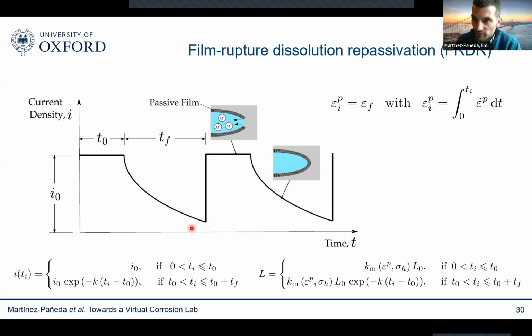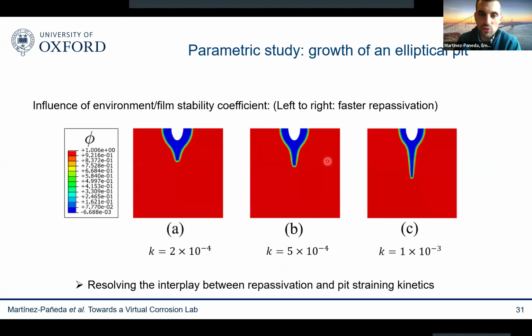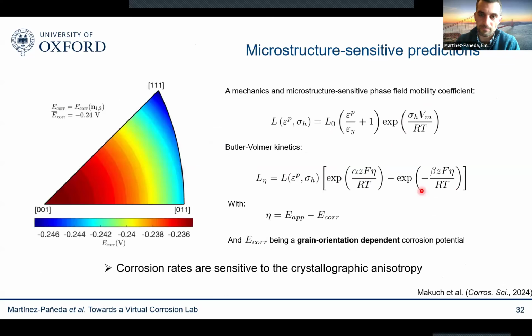And again, we can very easily incorporate this model into our framework because we can enrich again the mobility coefficient. We can make it a function of the corrosion current density and also the mechanical fields. We're solving a mechanical problem, so we know when we reach the critical failure strain of the passivation layer. And once you do that, then you can resolve this interplay between corrosion kinetics or dissolution kinetics and repassivation kinetics and straining kinetics. And you can see that we can reproduce typical results expected from the experimental literature. And we can capture naturally this pit to crack transition that the community has been trying to capture over decades.